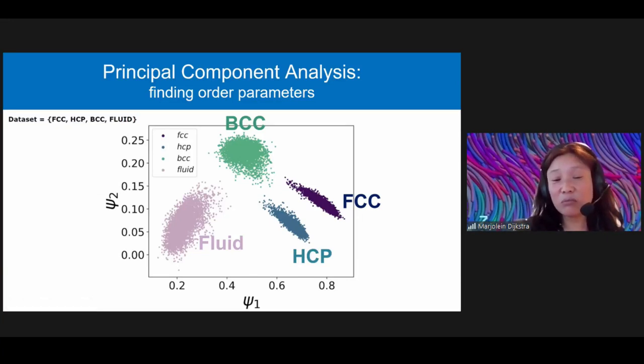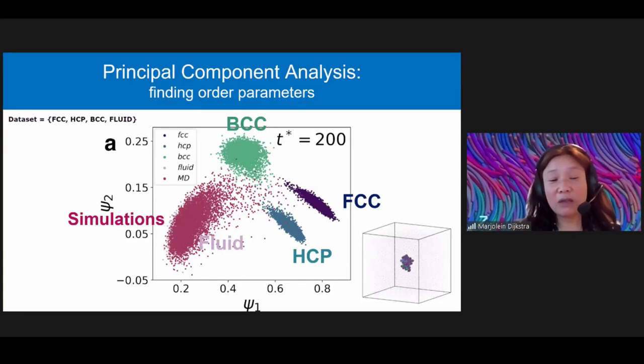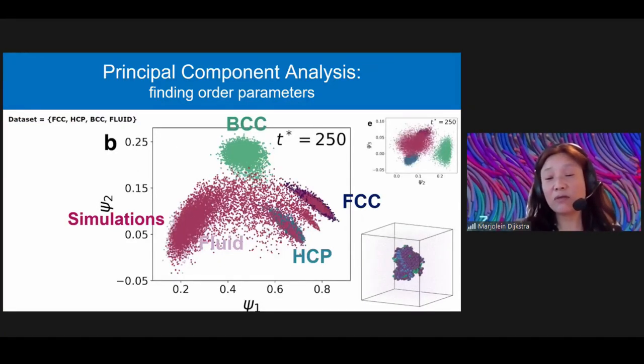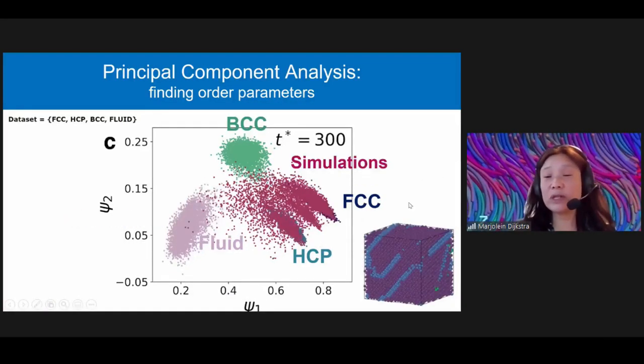And so if we then plot, for instance, a simulation trajectory, we find that if we start in a fluid phase, it goes towards the FCC and the HCP phase. There are stacking faults in the crystal nucleus, and that's why there are these three lobes here. But what we do see is that it completely avoids the BCC phase.